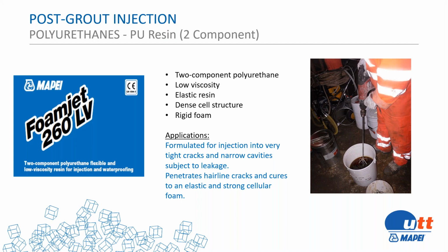We also have Foam Jet 260 LV. The LV stands for low viscosity. This is an elastic resin. It has a very dense cell structure. So sometimes a urethane can have a very high viscosity and you want to get it into a very fine crack. So this material you would use for that. You can use it on hairline cracks. Again, it's a two component material, and it also has a very strong cellular foam once it's cured.